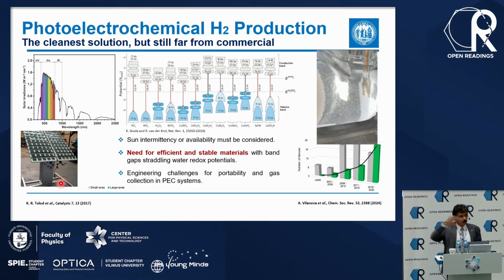So people have looked into a lot of different areas. They have looked into different materials. And then they realized that it is very difficult to find one single material which will give you the photovoltage that is needed to split water. It's not much. Theoretically, it's only 1.23 electron volt, but in a solution, if this is your reactor and you put two electrodes inside, you will need 1.5 because you have a resistance. Ions have to go from one side to the other side, and this diffusion barrier is imposing a penalty of 0.2, 0.3. So in reality, you need 1.5, 1.6 volt to split water.